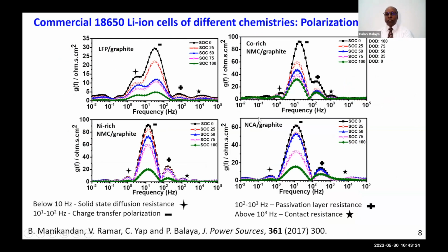You can see here. Let's just ignore cobalt-rich at the moment. We have no time. So I'm talking about LFP technology and nickel-rich NMC and then NCA technology. One can clearly see that there are 4 contributions. 1 at very low frequency, 2 middle frequency, 3rd, and the 4th. By doing various experiments, which you can see in our published paper, Manigandan's paper, one can clearly see the major contribution is because of the charge transfer happening on the positive electrode, which is the cathode. So you can see here, this is the major contribution. And interestingly, the same contribution is seen also in oxide chemistry. All these are basically charge transfer reactions at the cathode side.